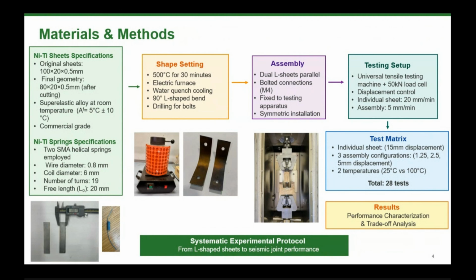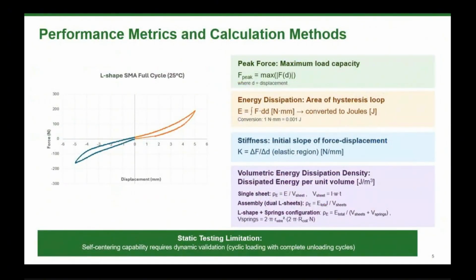The temperature of the environment was 25 degrees Celsius and 100 degrees Celsius. Before talking about results, I show you one of the 28 graphs that we obtained from this kind of tensile testing. You can see how the sheets have the flag-shaped diagram with hysteresis loop, which we talked about before.